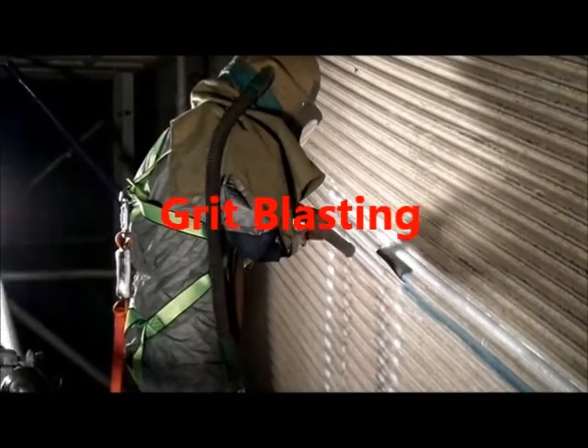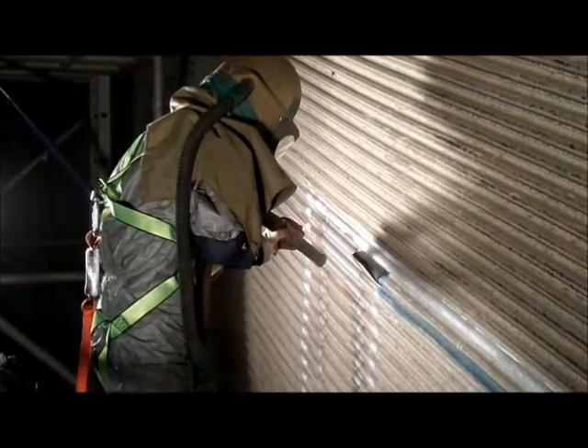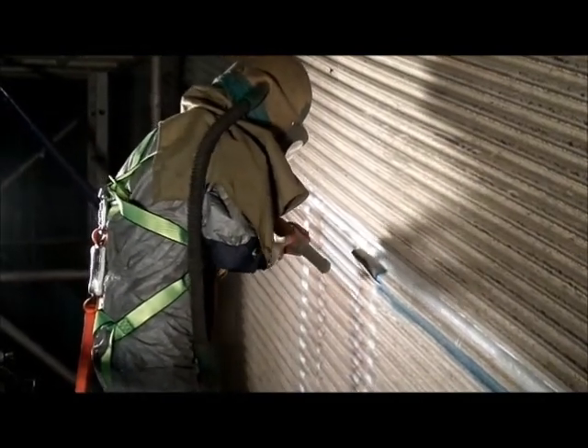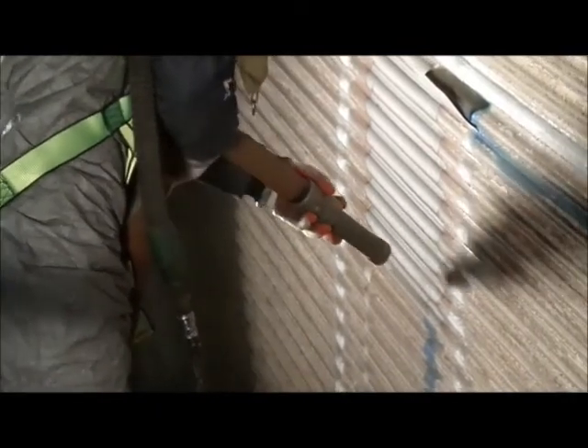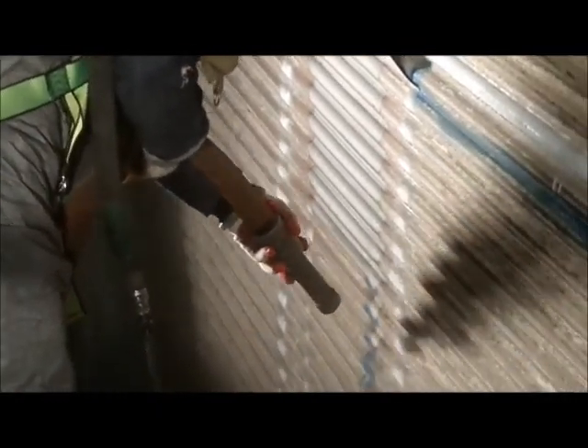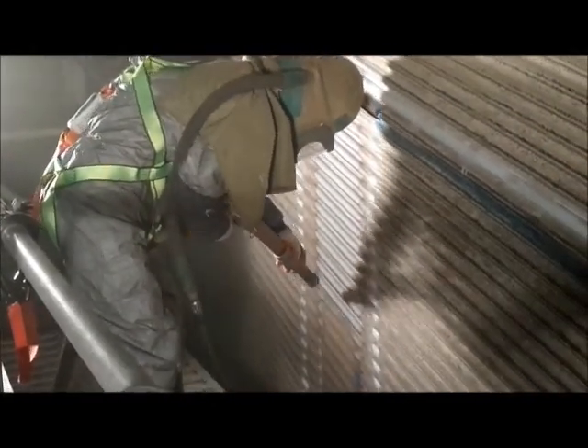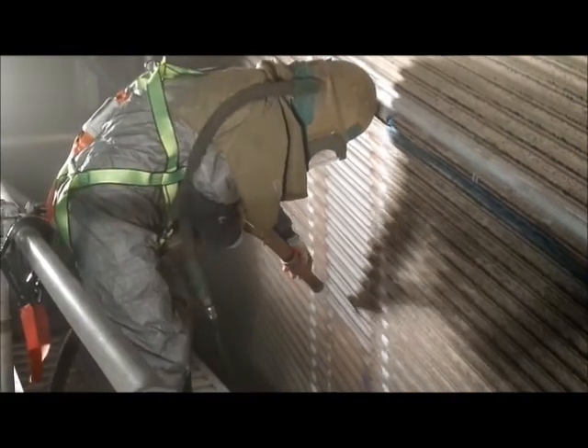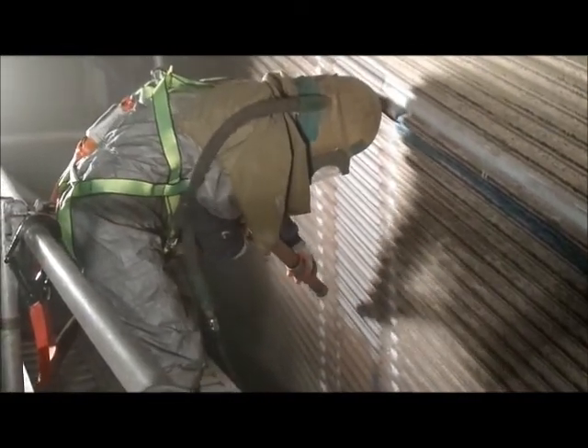Grit blasting. For better adhesion of sprayed material to the surface of base metal, proper surface preparation is required to provide a better anchoring effect of the deposited coating layer to the base metal surface. For this reason, grit blasting by bond particle should be done to make proper surface roughness with accompanying descaling.